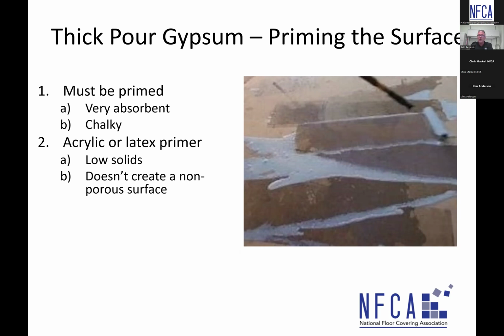The point that I want to make, though, is that these low solids acrylics or latexes don't create a non-porous surface. They're basically being applied to the surface to equal out the absorbency of the gypsum, to allow sufficient open time of your flooring adhesive, especially for the wet set or semi-wet set materials. It's so that the gypsum doesn't draw the moisture out of the adhesive, and you have ample working time with the adhesive. So it's very, very common for a primer to be installed once the gypsum is cured and dry.